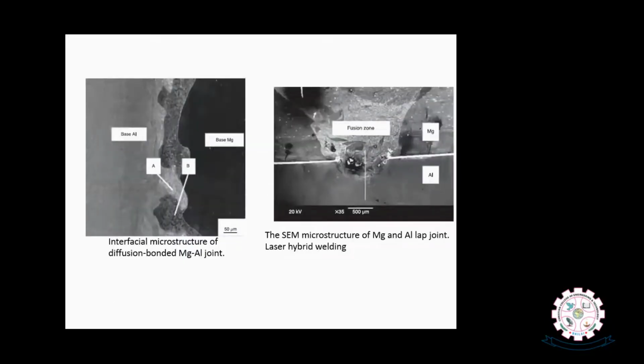Here you can see typical microstructures at the cross sections of magnesium aluminum joints. You can see on the left side the interfacial microstructure of a diffusion bonded magnesium aluminum joint. On the right side, you can see the cross section microstructure of a magnesium aluminum lap joint obtained by laser hybrid welding. You can see both the base materials, aluminum as well as magnesium, are mixed at the interface, and you can see here some zones on the left side, A and B, where magnesium has dissolved in aluminum as well as aluminum also dissolved in magnesium, and result in some solid solution grains in addition to the formation of intermetallics.